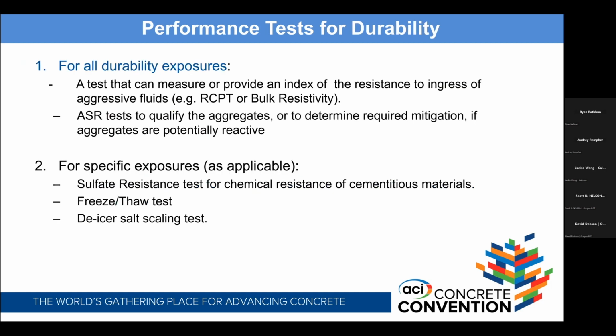So what are the performance attributes? Other than strength, for durability, we want something that indicates the resistance to ingress of aggressive fluids, whether it's chlorides, sulfates, or whatever, or acids. The ASTM C1202 or AASHTO T277 or a bulk resistivity test would provide some index of that resistance. And those are being adopted. The Canadian standard uses rapid chloride permeability limits. Now we're introducing bulk resistivity limits as performance measures for durability requirements.